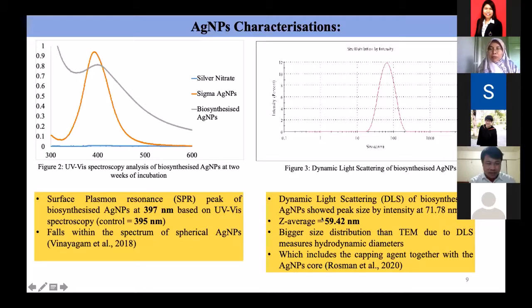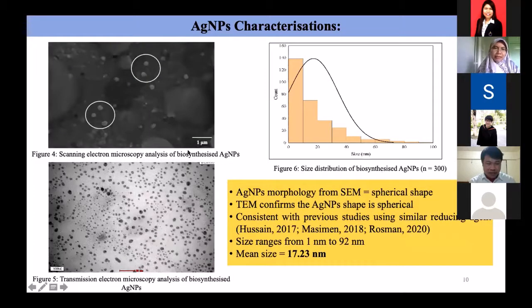And then we want to measure the size of the nanoparticle briefly. So we use DLS. From the DLS analysis, we found the average size was 59.42 nanometer, but it is only a rough observation. So that's why we still need TEM to measure the actual size of the nanoparticle. So we use SEM and TEM to confirm the morphology and also the actual size. From the microscopy analysis, we confirm through SEM that our silver nanoparticle was spherical, and their size was 17.23 nanometer. That's the actual size of our silver nanoparticle synthesized from the polychaete.